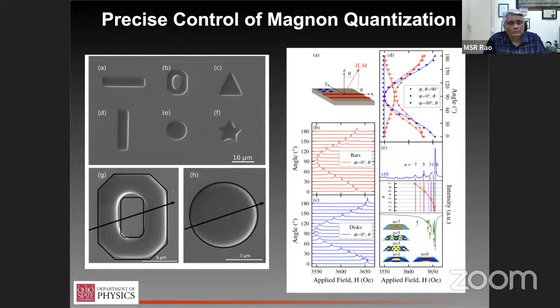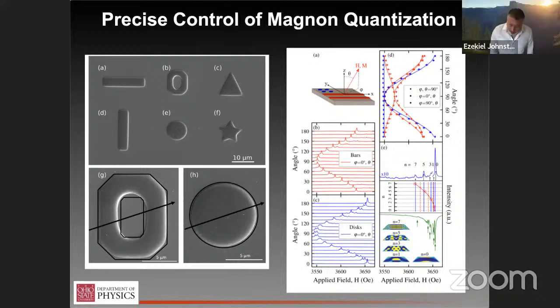Probably one could also do inverse spin Hall effect to see the effective thickness, I suppose. Yes, so that's a whole different direction of research that I didn't even have the chance to talk about. So this material really is amazing. And it turns out, the Utah group has done ferromagnetic spin pumping into platinum and measured an inverse spin Hall effect that is very measurable.